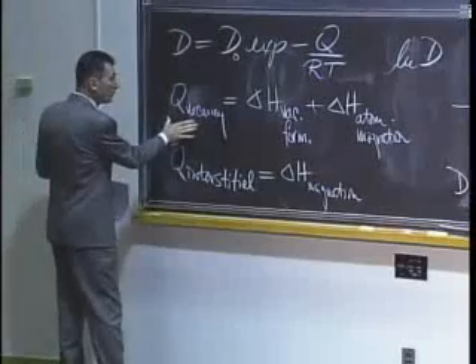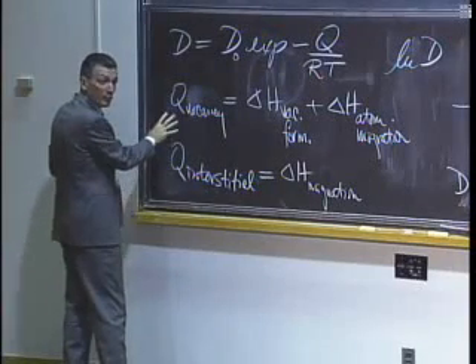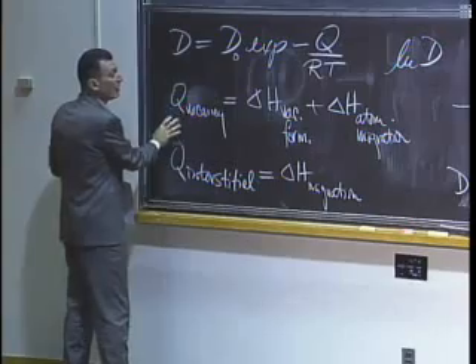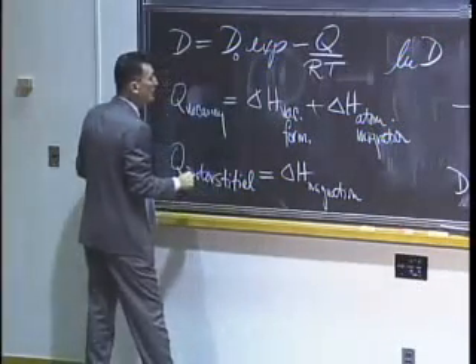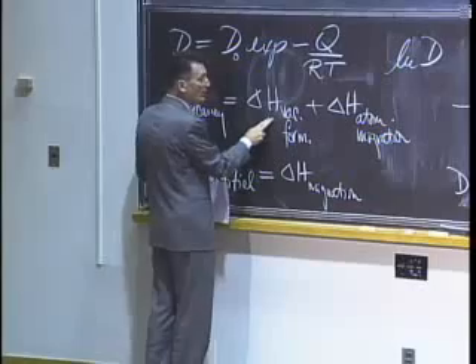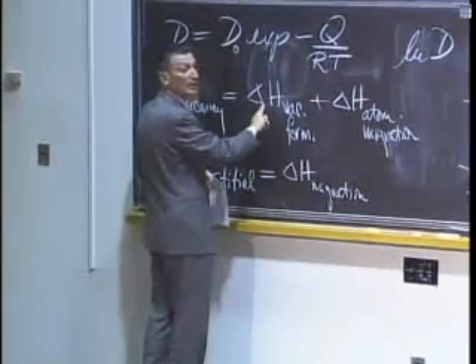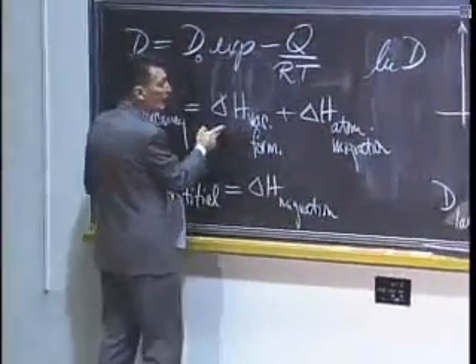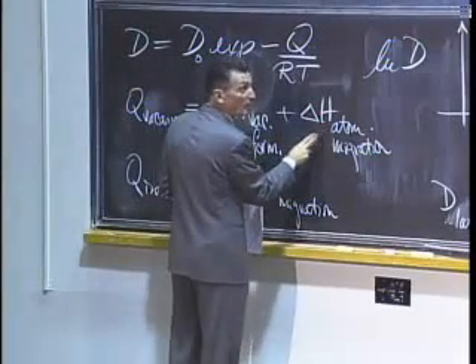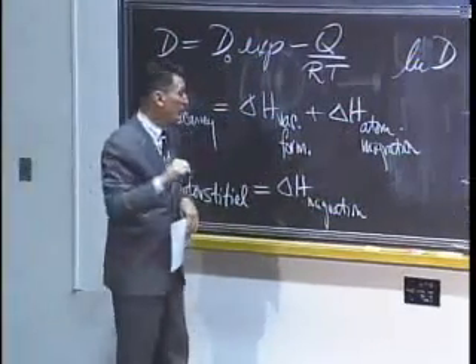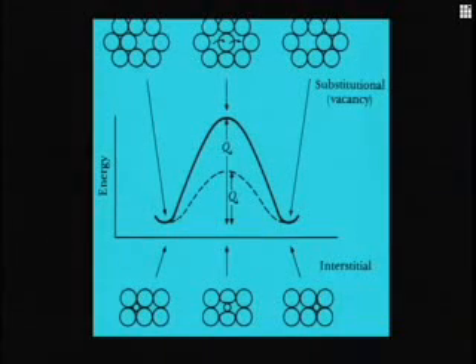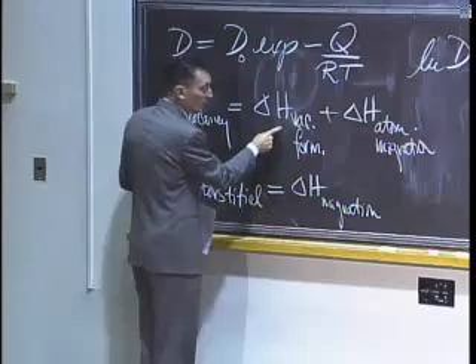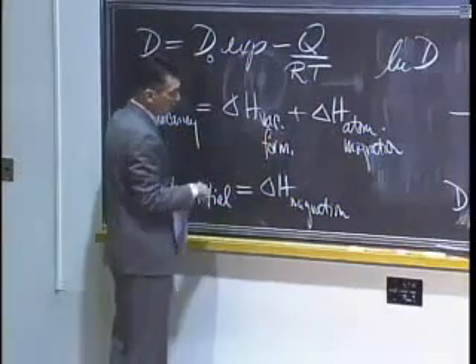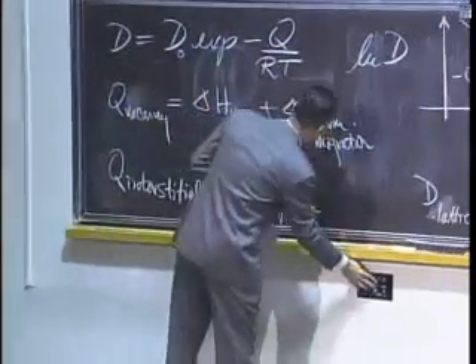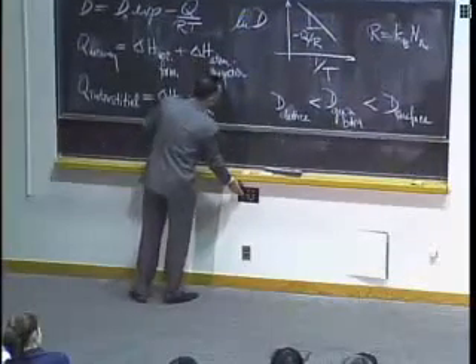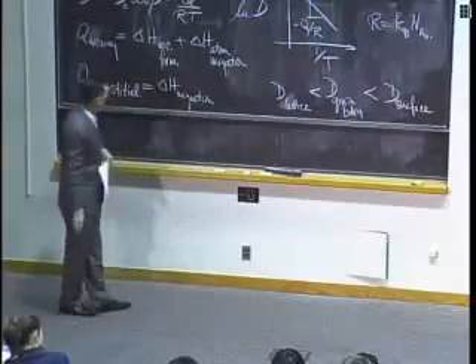And when we looked at the atomistics further, we reasoned that when we have diffusion by vacancy jump mechanism, this activation energy up here in the equation is the sum of two components, one being the enthalpy of vacancy formation, which is really the negative of the bonding energy, and then the energy associated with the atom migration, which is the energy of squeezing through that saddle point shown in the figure. In the case of interstitial diffusion, we don't have to form vacancies. There's enough vacant sites by virtue of the fact that we've got so much free volume, even in a close-packed solid, so we're really just paying for the enthalpy of migration.